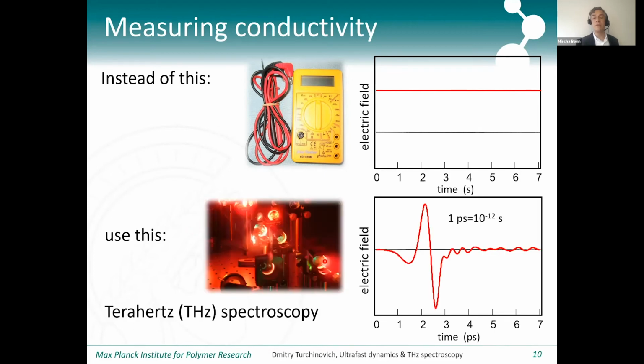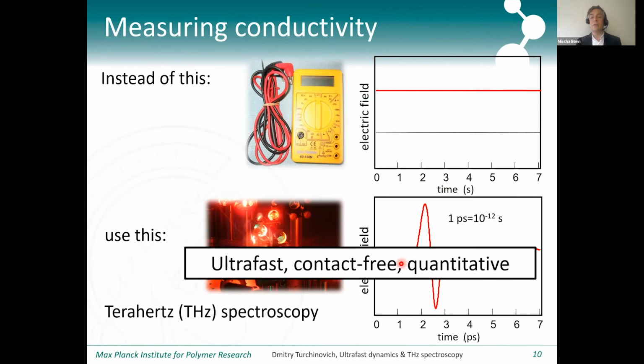The idea is to use terahertz spectroscopy, which is essentially a single cycle, a single oscillation of the electromagnetic field that can propagate freely through space. The field is only on for about a picosecond. It has a couple of advantages in terms of measuring conductivity, because it's ultra fast: the field is only on for a picosecond, so we can also look at changes on that time scale. It does not require contacts because the pulse is freely propagating. And I will show you, it also allows you to determine charge carrier density and charge carrier mobility in a quantitative fashion in a relatively straightforward way.